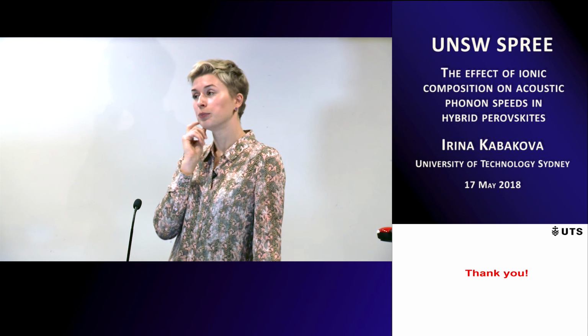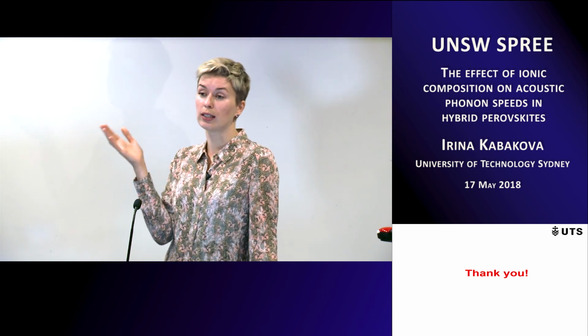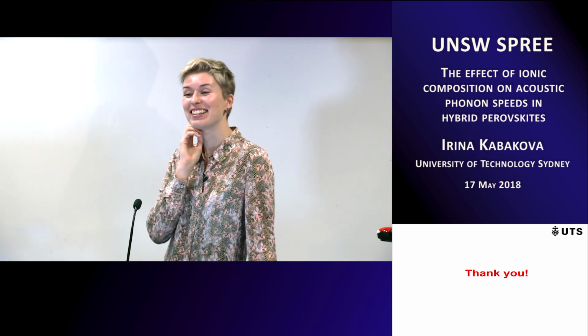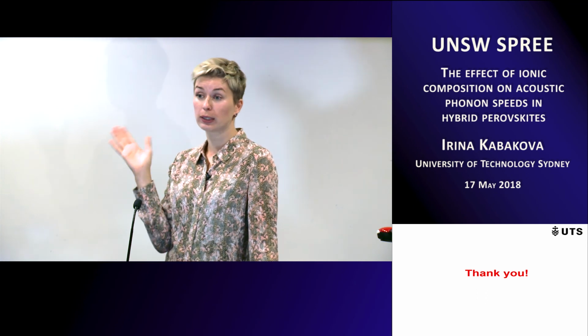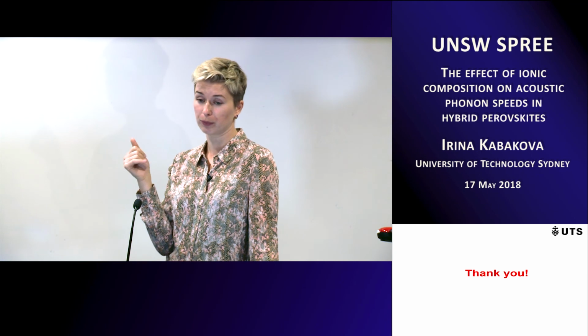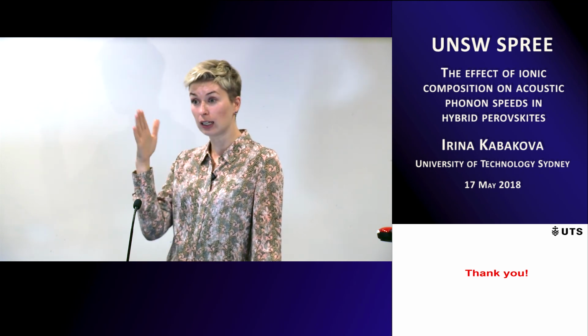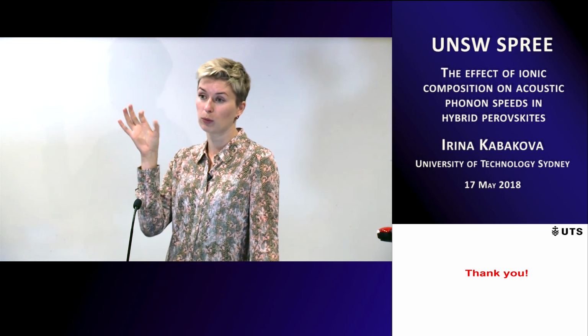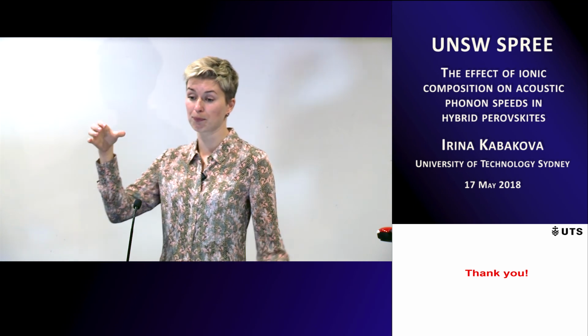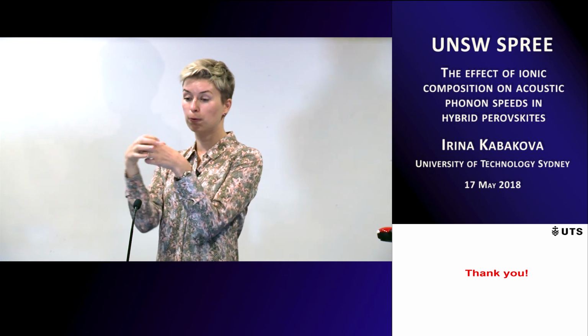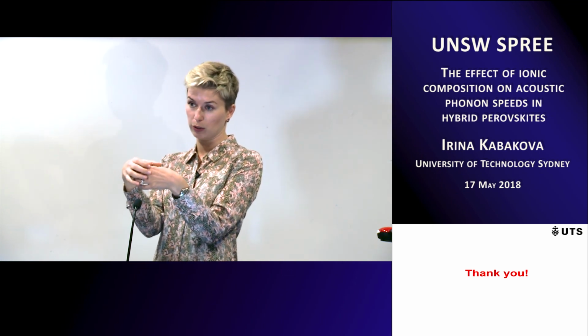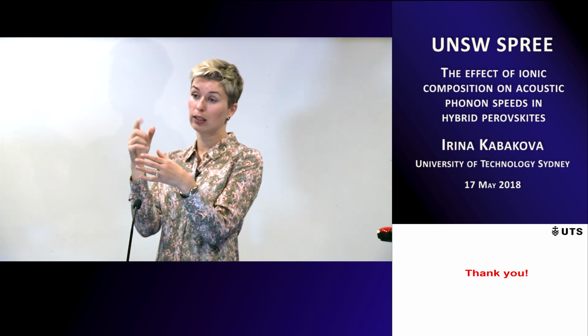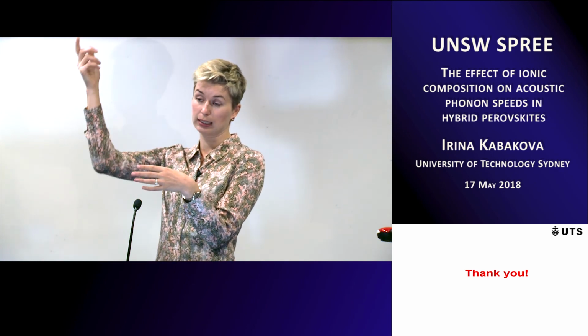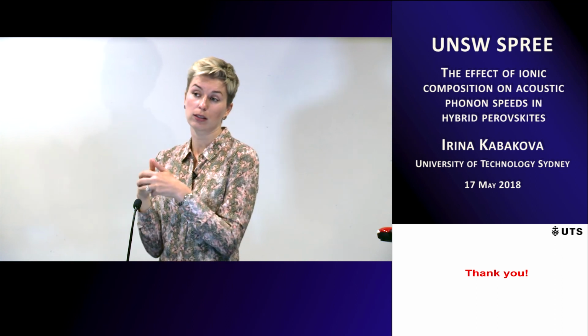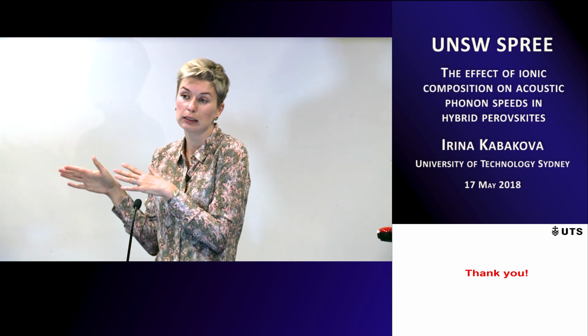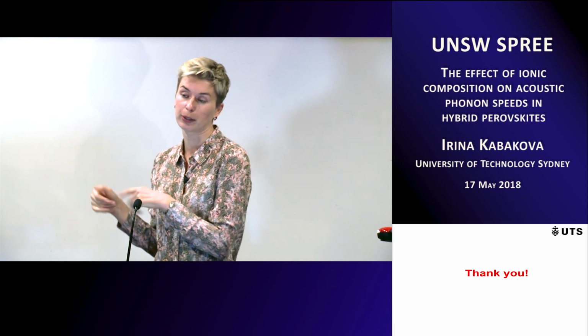I see. Well, I guess it's always one way to find out. Let's try, and then we find out. But if there is a preferred orientation, then you will see it. You will definitely be able to get information about this orientation and align with it. It might be that the peaks will be broader if, for instance, we are talking about interaction within a focus volume, where the light interacts with acoustic waves, and if there are different domains of different orientation, they will all send scattered light that you collect and analyze, which leads to peak broadening. But that's the only issue that might be. So the results might not be that clean, but nonetheless you still get some information.